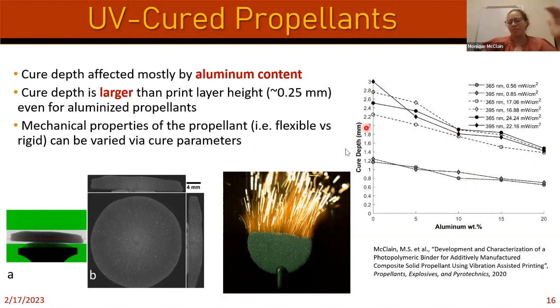But in general, there's a lot more work to be done in understanding essentially what's going to happen with these cure depths, because if you cure layer by layer, now you're going to have these interfaces between your print layers, and it's not necessarily going to be as strong as if you just had something completely cured altogether, like with traditional isocyanates and HTPB. So there are definitely challenges with trying to figure out how do we improve these mechanical properties.